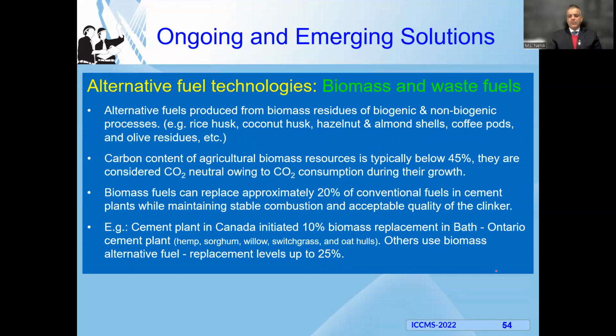Among the common ones, or the most known ones, is the use of biomass as fuels. Biomass could be from agricultural biomasses, for example. Agricultural products typically have a certain fixed amount of carbon, maybe about 45% or so, but they're perceived as neutral in CO2, because they capture that CO2 through their growth. So what is the rationale behind perceiving them as a green source of energy? By resorting to such sustainable biomass fuels, maybe we could reduce the CO2 related to energy consumption of cement, maybe somewhere around 20% or so.